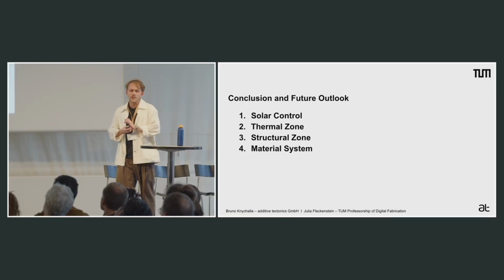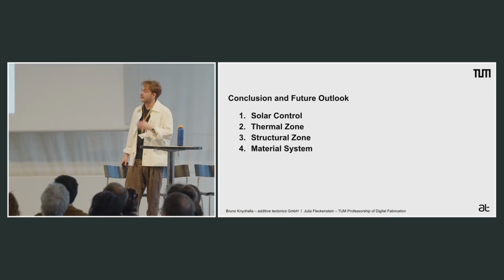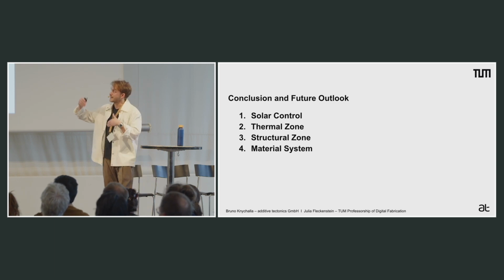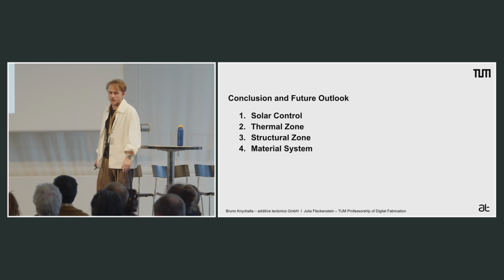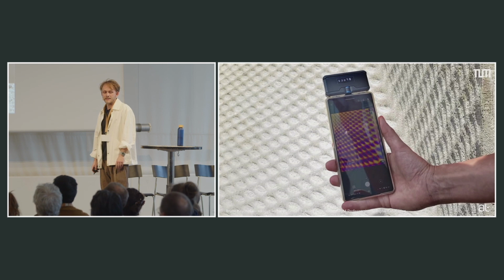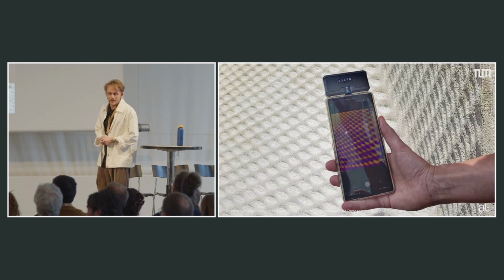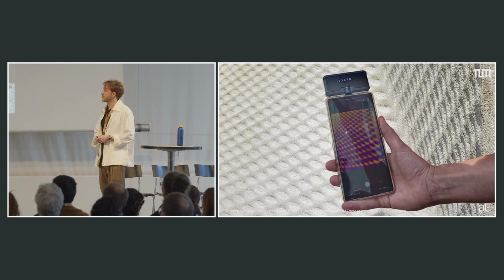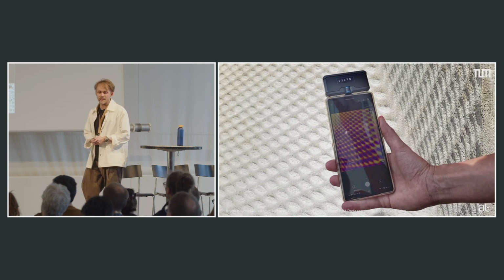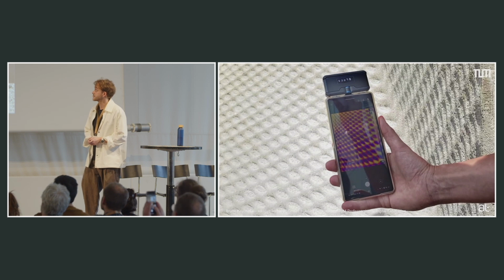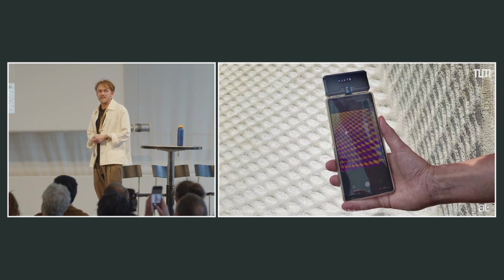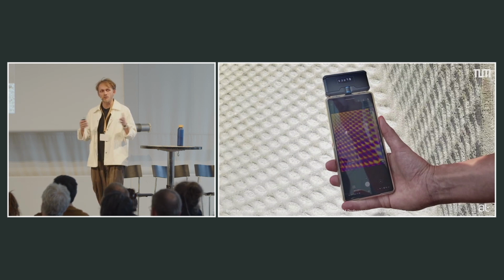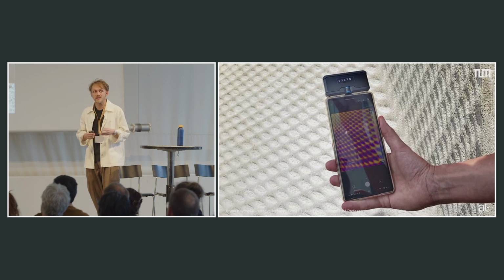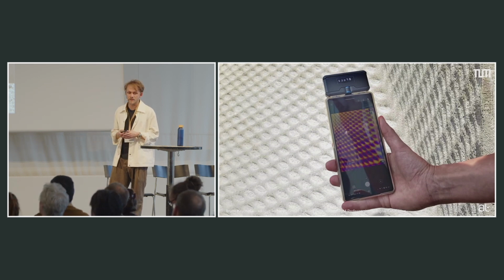For my conclusion and for the future outlook, I will separate it again in these 4 points that I discussed before. Firstly, the surface measurements were very successful. The self-shading behavior worked quite nicely and shows very promising results. But these measurements should be applied for the whole cross-section and not just for the surface, to see how the heat actually transfers through the element.